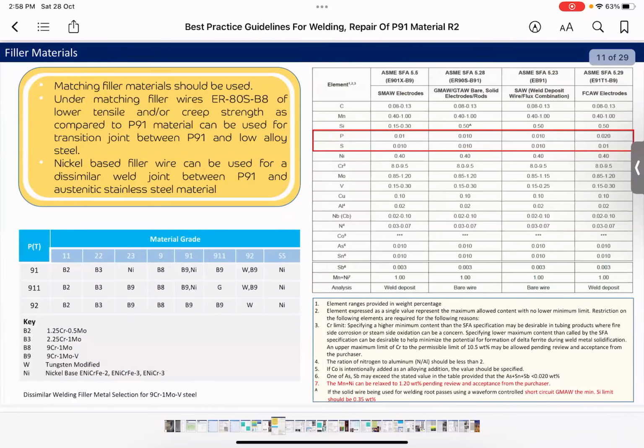Filler materials. For filler materials, I have 3 points here. The first one is the matching filler wire. So we should always use matching filler wire, but I know that this is not always possible. Sometimes we might have dissimilar weld joints. We all know that dissimilar weld joints are not recommended, but in many cases they cannot be avoided. So for welding P91 to another low alloy steel, we should use undermatching filler wire for the weld joint. We should butter it.